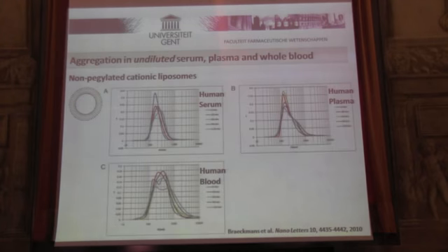And what you're looking at here are those relative size distributions. So this is the relative fraction of different sizes of liposomes measured in serum, plasma and blood as a function of time. The colors mean different time points. We inject it and we take samples at different time points. In serum you see, as a function of time, slight aggregation, not unexpectedly, but in plasma it's already much worse, and if you go to the whole human blood, it's an order of magnitude worse.